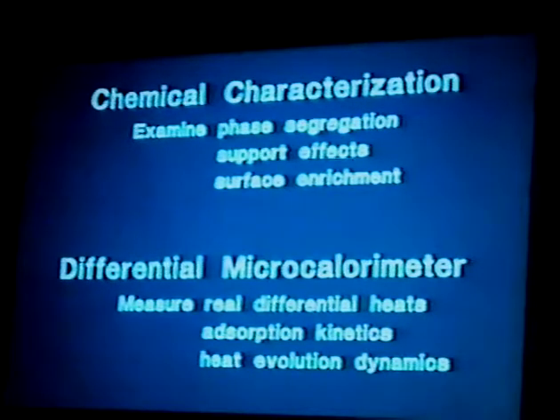A technique that we decided to try and use to establish the nature of the surface was differential adsorption microcalorimetry. The calorimeter that we developed was able to measure real differential heats of adsorption as a function of coverage. And in addition, we were able to get adsorption kinetic information for each dose and changes in the kinetics as a function of coverage, and also some heat evolution dynamics. And I'll just briefly describe the system.